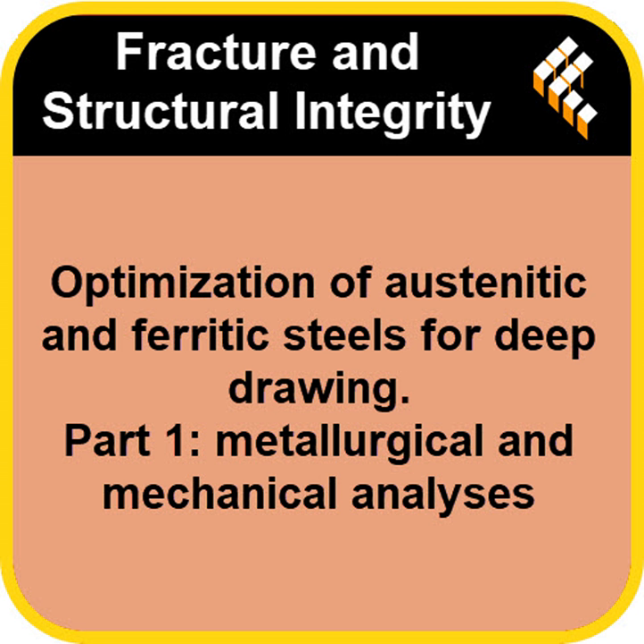Which sounds good, but in deep drawing, you need the material to keep deforming, right? To stretch without breaking. Precisely. And that's where the austenitic grades, the 304s, really shine. Their basic crystal structure, the FCC lattice, it just makes them incredibly good at plastic deformation. They can stretch a lot more. A lot more. And they have this amazing ability to work harden. The more you stretch them, the stronger they get. That's linked to something called the strain hardening exponent, which is much higher for austenitics.